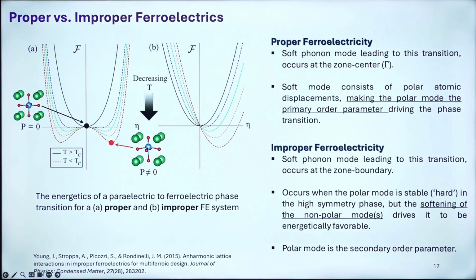We are connecting it with the order parameter, and then we can see that there is a mode which is trying to become imaginary, and then of course one can freeze that particular mode. I will show what we have done, and then we have to compute the energies as a function of displacement or distortion. Now the improper ferroelectrics,